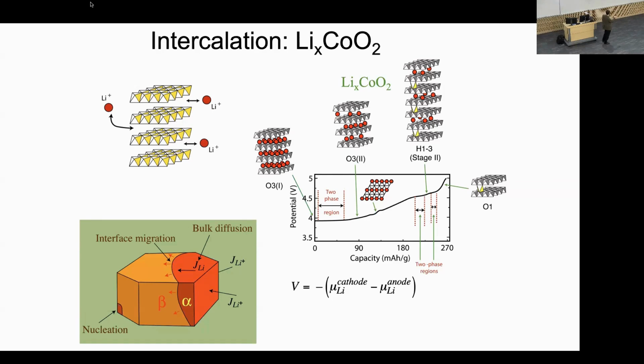And so here the axis is inverted. This is fully lithiated, looks like this. And then when we're moving in this direction, we're pulling out lithium and introducing vacancies. And you can see there's a lot of features in this voltage curve. So in the beginning, you see a plateau, and that means you get a two-phase reaction where you go from a fully lithiated to a partially lithiated phase with a lot of vacancies. And that happens in a two-phase reaction. And then you have a solid solution, a sloping region, where you just have disorder between lithium ions and vacancies.